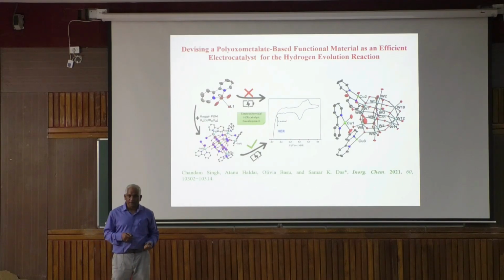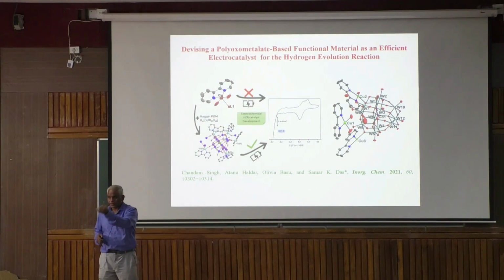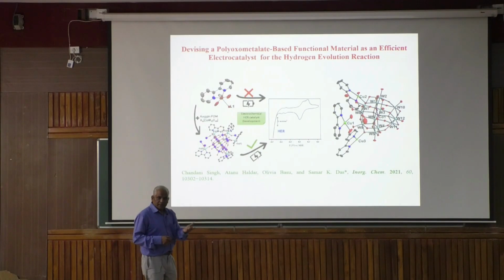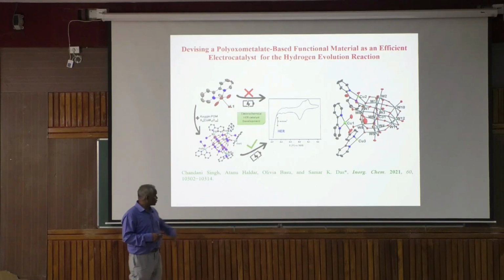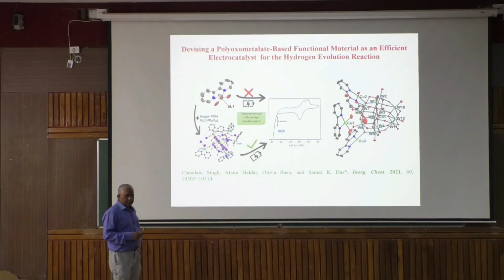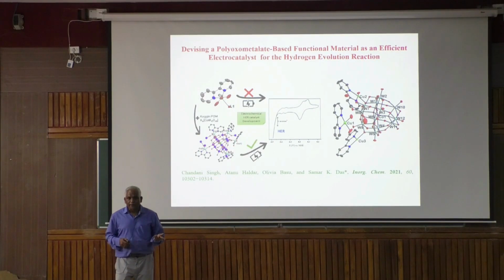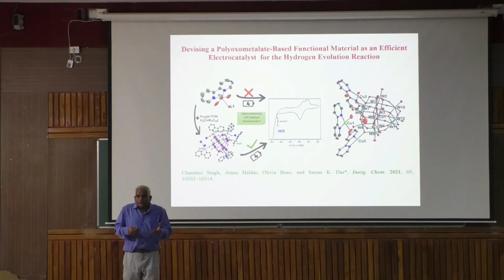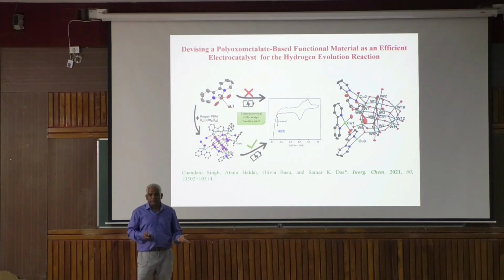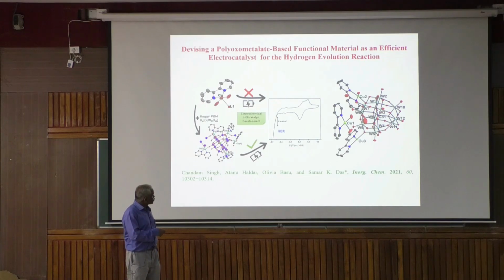We don't get oxygen. Gas comes when we put it in the GC. We see hydrogen happening in the cathodic window. We believe that we should respect the soft and hard acid-base principle because copper is soft in nature and a couple of bipyridyl ligands are there. So it will like to be reduced rather than be oxidized because of its soft nature. So copper 2 will go to copper 1, and copper 1 will be a very good reductant.